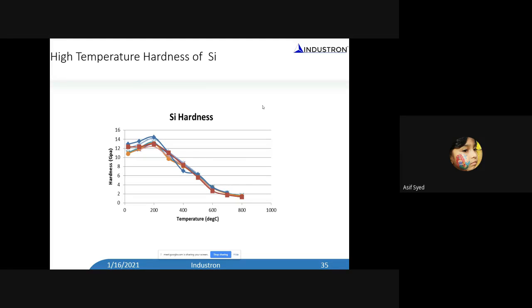In silicon, it's a little bit of a mystery. The hardness initially increases up to 200 degrees C and then decreases. This is mainly because two things happen. In silicon, when you indent, there is a stress-induced phase transformation, and at higher temperature you also have slip-based plastic deformation. So there are two competing mechanisms, and because of that, you see a peak, and then the hardness decreases. With that, we were trying to understand more about silicon.